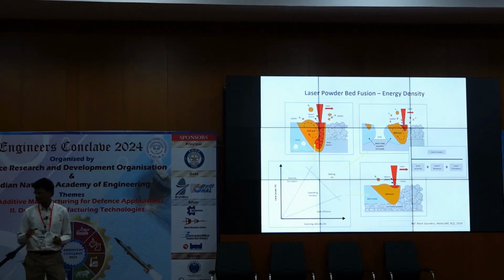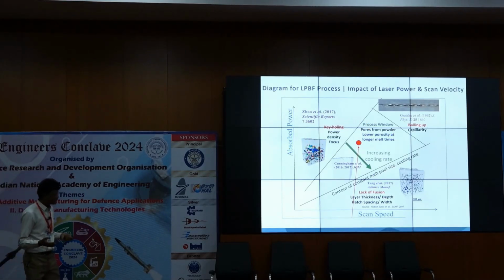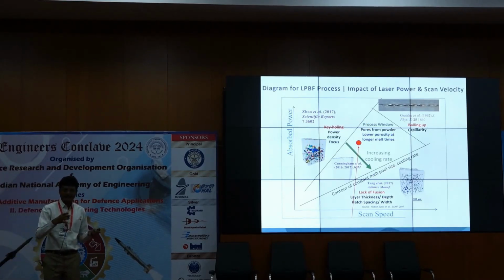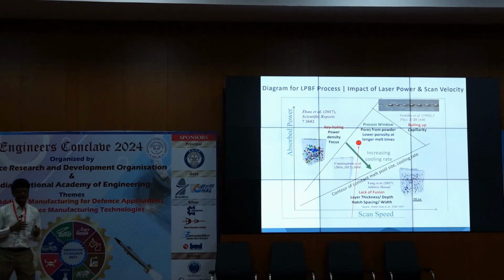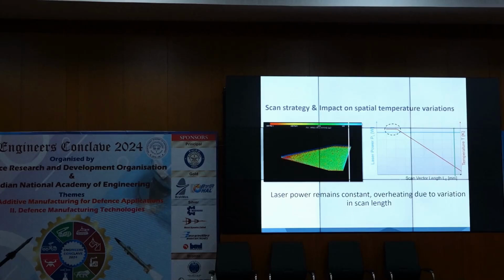So we start plotting these PV diagrams, the laser power on one axis and the scan speed on the other axis. And by various permutations and combinations, you can demarcate 3 different zones wherein if you are applying less energy, you may lead to the lack of fusion. If you apply too much energy than what is required, you may get into the keyhole regime. And in between, a small space is called the optimal process space wherein you can confidently work. But incidentally, the system or the process is much more complex than that.